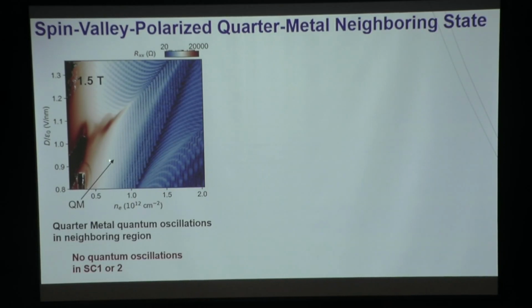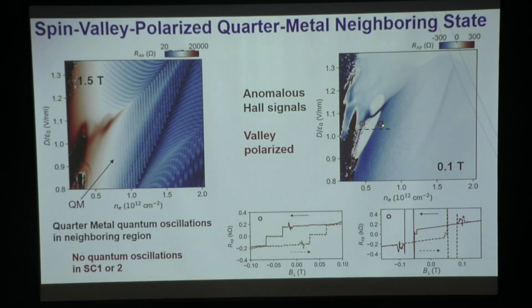And there are further analysis we can do. As I was telling you, you can do quantum oscillation measurement to figure out the degeneracy at the Fermi surface. And you find that in this big region here, neighboring the superconductor, we got so-called quarter metal, which means 1 out of the 4 spin valley degeneracy is occupied. And that agrees with what we expect from the flat band and correlation effect. On the other hand, this neighboring state here also has anomalous Hall signal, and that immediately tells you it is valley-polarized. And you have this hysteresis, okay? Orbital magnetic. So that tells you at least this neighboring state here, we should think of it as a spin and valley-polarized quarter metal.